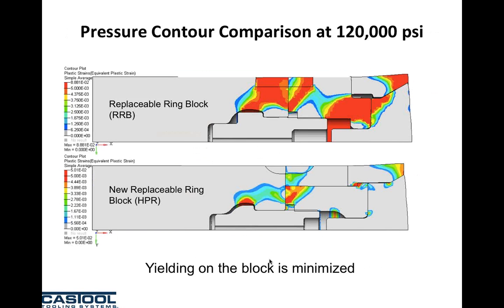And this one, the quick study shows that on the top is the replaceable ring dummy block at 120,000 psi, and the bottom one is the new replaceable ring at 120,000 psi. The yielding on the block is minimized so that the block is able to function properly, open properly, and collapse properly, with repeated cycles at 120,000 psi.